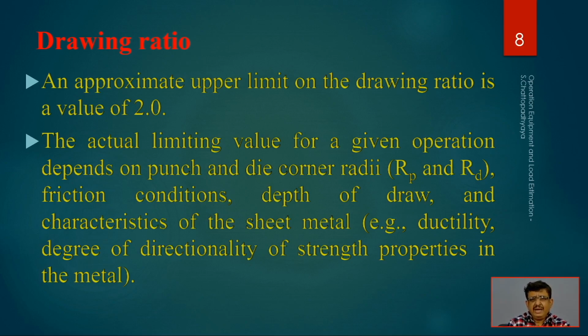The corner radius of the punch, R suffix P, and the corner radius of the die have a role to play in the friction conditions and the depth of the draw. That depth is also important, and so are material characteristics, because we can do these operations only where the material is ductile. Better the ductility, easier the drawability. The degree of directionality of the strength properties, how the strains are implemented, and their manifestation in the grain structures of those metals also have a role to play, because all materials are not equally ductile. Wherever ductility is higher, the drawability is higher, and the strength properties also have to be critically analyzed before establishing the deep drawing process.